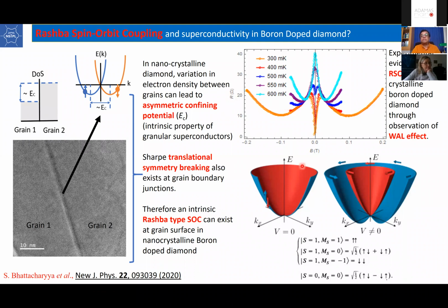If you perform the magnetoresistance of the material, you can see a positive magnetoresistance. And this is, it's well known, weak anti-localization. This is the signature of spin orbit coupling in the material. Now, what does it mean? It means that you can have the spin singlet, just like a BCS superconductor, S equals 0. Now you can have, in addition to that, S equals 1, the total spin equal to 1. So you can have spin up, spin down, and a linear combination. And this is very rare to see in materials. In superconductors, we have been very fortunate to see this effect.